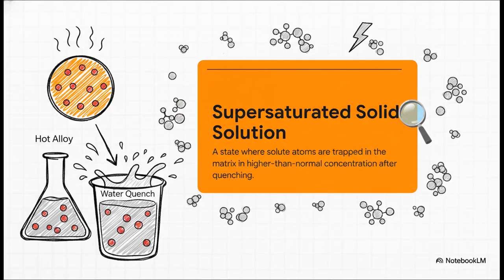Next, step 2, quenching. We take that fiery hot, perfectly mixed alloy and plunge it into water, cooling it down incredibly fast. This is the critical move. That sudden temperature drop freezes everything in place. It doesn't give those copper atoms any time to escape. Instead, they get trapped inside the aluminum's crystal structure. This creates something called a supersaturated solid solution, basically an unstable, supercharged state that's holding way more copper than it ever should at room temperature.